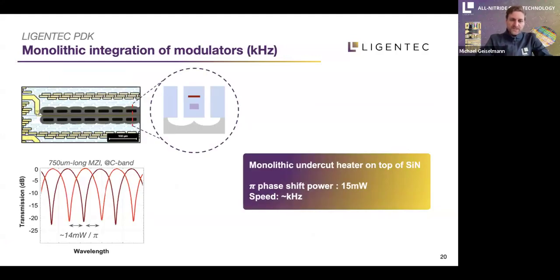A new process module that we have introduced in the beginning of the year is undercut module, where we address the monolithic integration of modulators in the kilohertz range. And here we take away the silicon from underneath the waveguide. So you have a better isolation. And the red one here, that's the heater. The purple one, that's the silicon nitride. And here that is then air, what we then call an undercut of the process. And this monolithic undercut heater on top of the standard silicon nitride process gives high phase shift powers of 10 to 15 milliwatts and speeds of a few kilohertz.